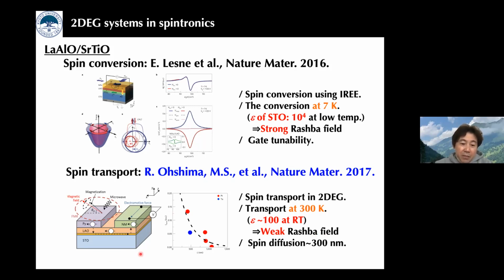And we fabricated such a spin transport device, where we use the spin pumping technique, and the spin current is injected into the 2D system, propagates in the 2D, and is absorbed in the separated non-magnetic electrodes, which have a sizable spin-orbit interaction. We detect the electromotive force from the inverse spin Hall effect by the injected spin current. By measuring the output signal as a function of the gap length, we estimated the spin diffusion length in this oxide 2D to be 300 nanometers at room temperature. The details are described in this paper published in 2017.